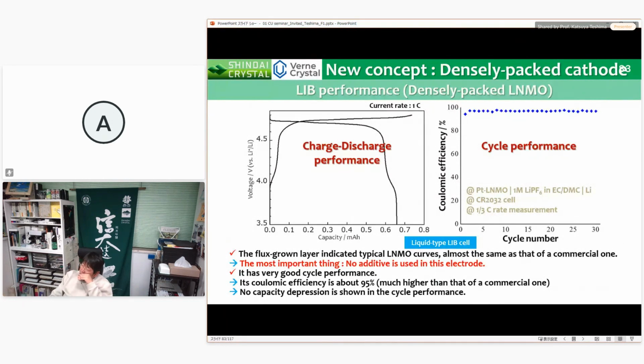These are the LIB performances of the densely packed LNMO crystal layers. The flux-grown LNMO crystal layer indicates typical LNMO curves, almost the same as that of the commercial one. Most importantly, no additives are used in the electrode, and it has very good cycle performance. Its coulombic efficiency is about 95%, which is much higher than that of the commercial one.